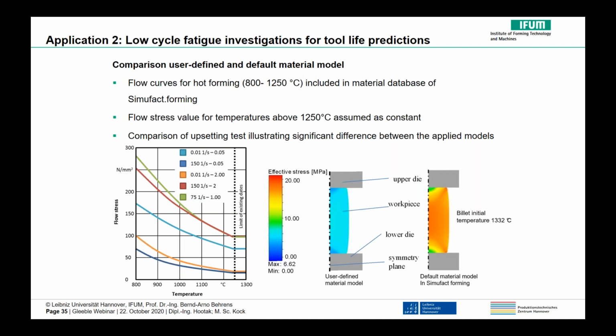And the comparison of upsetting tests illustrates the significant difference between the applied models, because you can see that the effective stress values in the workpiece material are approximately 3 times higher than the ones computed with the user-defined model. When the material temperature reaches the melting range, the flow stress decreases clearly. This aspect is not considered by the default material model, as the flow stress is assumed as constant for temperatures exceeding common ranges of hot forming, in this case above 1250 degrees C. And this could be verified by upsetting tests of semi-solid specimens applying the Gleeble system. The forces were much lower than the computed ones using the default material model from the database.